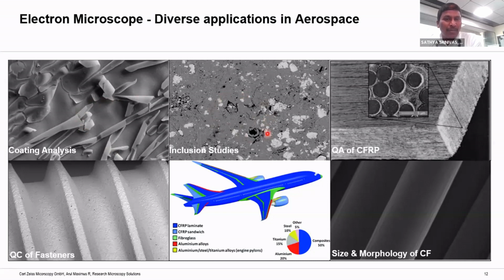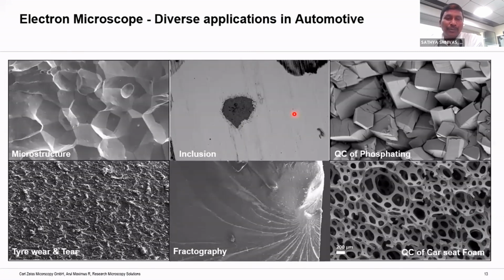And this is what I was talking about, the material contrast. Here you can see the different contrast in the image itself. If you have dark spots, which are low Z material, from the image itself we can understand whether it is corrosion, or some low Z material on a particular alloy. So you can clearly understand the surface features at a very high resolution. You can even understand the material distribution in a particular alloy, right? So these are a few applications in aerospace engineering.